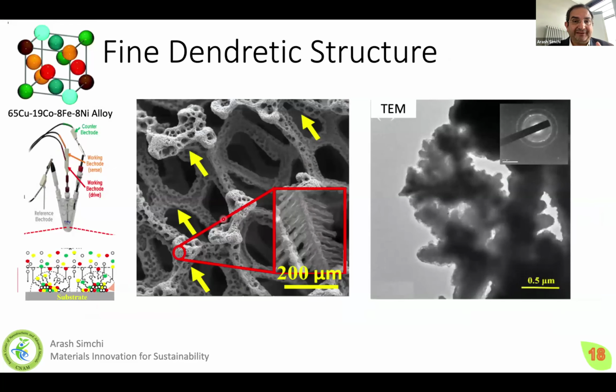And I would like to show you two simple examples. The first example, what we have done to learn from nature, is to make fine dendritic structures as we see in leaves. I would like to show you a copper alloy, which we have developed in our lab. And we show that these copper alloys can be produced by electrochemical deposition, as you see here. So we create a solution of different cations: copper, cobalt, iron, nickel. And then with an applied potential, we can deposit the catalyst on a substrate to have a higher active surface area. And if you look at this small system at a high magnification, it's a dendritic type structure, as you see in the TEM structure. So the surface area is quite high. And we learn from nature that we need a high surface area for catalytic activity.